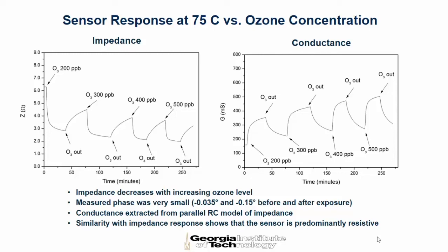So we cycle it from 200 to 300 ppb. You see that it is very, very repeatable, and you get a really nice fast response of the order of only 15 minutes.